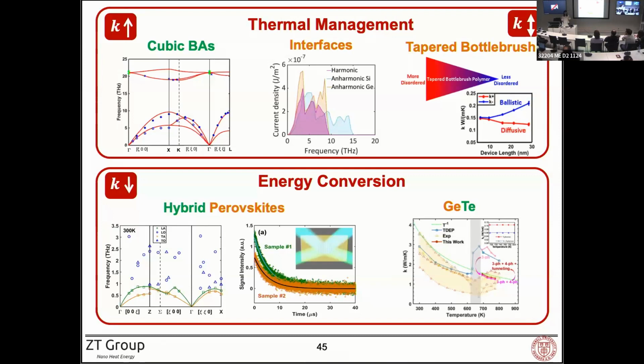First, if you create these superlattices, you might create this coherent effect. So what we are getting would not be just a single interface effect, but because of the coherent phonon transport, you might get much lower interface conductance than the single interface. And the second thing is the extrapolation. We might need to consider the size effect of the individual layers as well, because if you use small or thin layers, the thermal conductivity will not be the same as the bulk. So I think those two things also need to be taken into account.